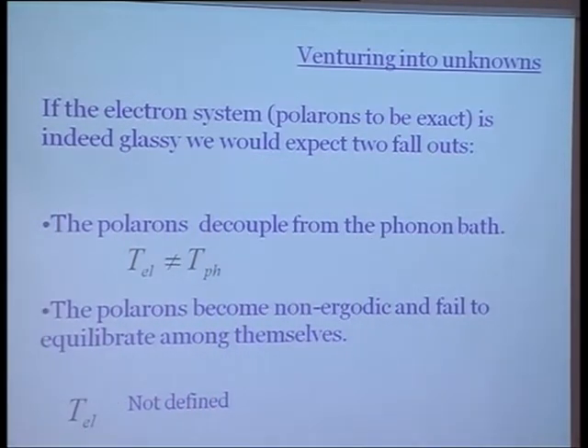Like I was talking to Vikram during the tea time, in this kind of systems, which you call electron glasses, what happens to the fluctuation dissipation theorem? Two things can happen: the electrons can decouple from the phonon bath. From the resistivity relaxation, we have a clear evidence for that. But it can also happen that at some limit, even the electrons themselves cannot equilibrate among themselves, and you get to a totally non-ergodic region.